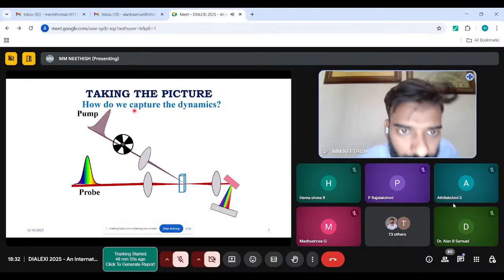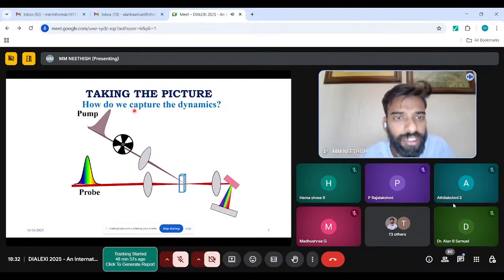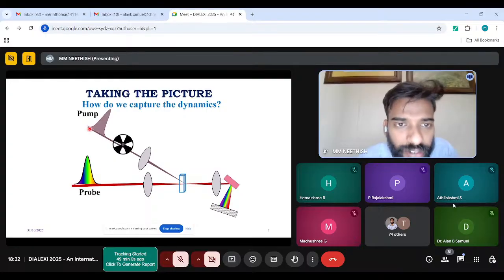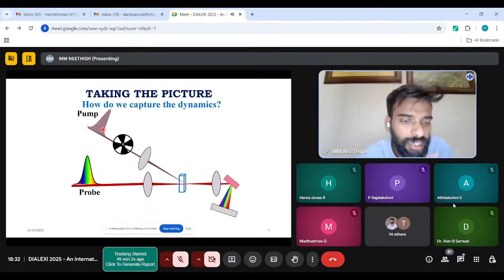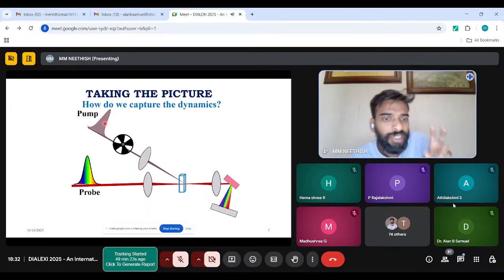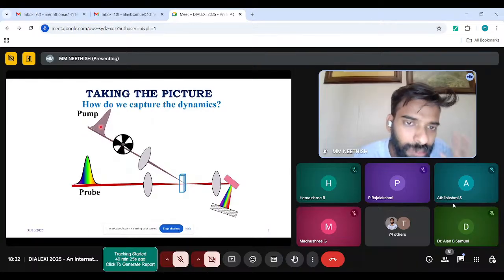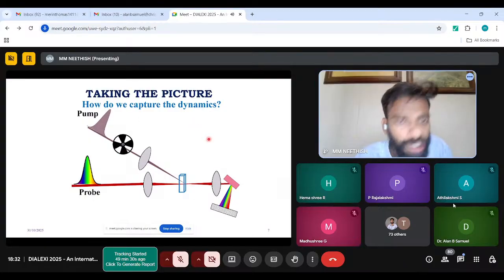So this is how it works. But there is a bottleneck. The bottleneck is that to do this, you need to have a femtosecond laser beam, femtosecond laser pulses, because the camera needs to act faster than the reaction or the evolution. So if the evolution is 200 femtoseconds, the camera should be faster than 200 femtoseconds. So these pulses should be shorter in time. In effect, the bottleneck of this experiment is that you need to have pulses short enough to see the changes.